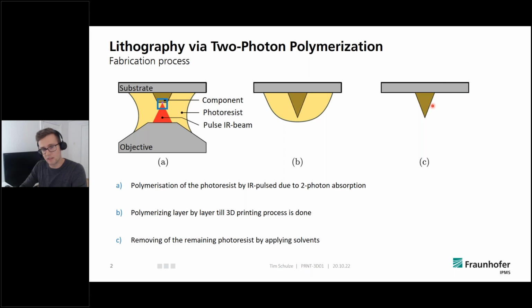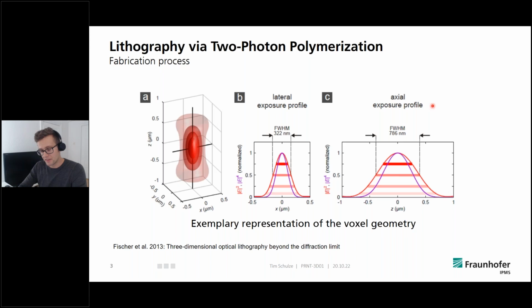Let's zoom in at the focus, the voxel, the volume where the polymerization happens. This volume is not really ball-shaped or circular. It's more like an ellipsoid, and the shape is indicated here. It has a smaller lateral width and a longer width along the axis, and it looks sort of like a grain of rice. This really needs to be considered when printing our structures.